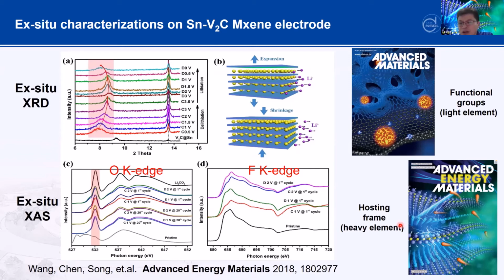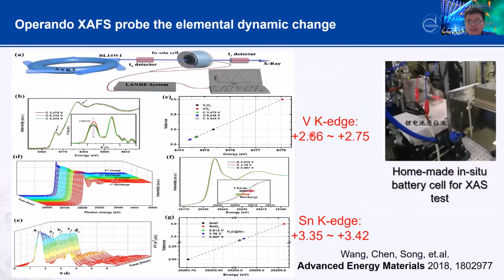really want to understand, does the metal atom contribute? So that's why we also try to build the homemade in-situ battery cell for XAS tests. Here we selected the tin intercalated with vanadium carbide. During the charge and discharge, we do the in-situ scan, and we selected the reference sample. We can calculate the valence value.